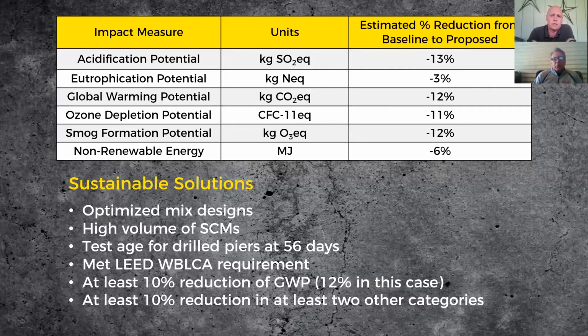And as a result, the project met the rigorous LEED whole building LCA credit by showing at least a 10% reduction in global warming potential, 12% in this case, along with at least 10% reduction in at least 2 other environmental impact categories. Now keep in mind, this is not just for concrete. This is for all of the structural and shell exterior envelope components of the building. So the concrete, to meet those criteria, typically you have to have a pretty significant reduction in the carbon footprint of concrete.